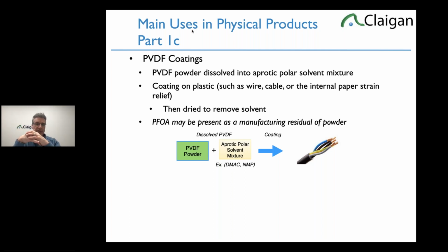And so we see it in electronics all the time because in a cable, the wires are often coated with it to make them frictionless so you can bend them. Or if you have that little paper strain relief that is very flexible, the strain relief paper will be PVDF coated. They'll say PTFE coated, but it's really PVDF coated. They're very similar, but that's a typical fluoro coating. And will the average supplier, which has a cable in their product, know it's in there? No. If you're doing data gathering with suppliers, good luck. These applications are well beyond the knowledge base. And it's probably one of the most common places we find fluoropolymers, inside cables, because they coat them lightly, the cables for the strain relief, and that adds the low friction.